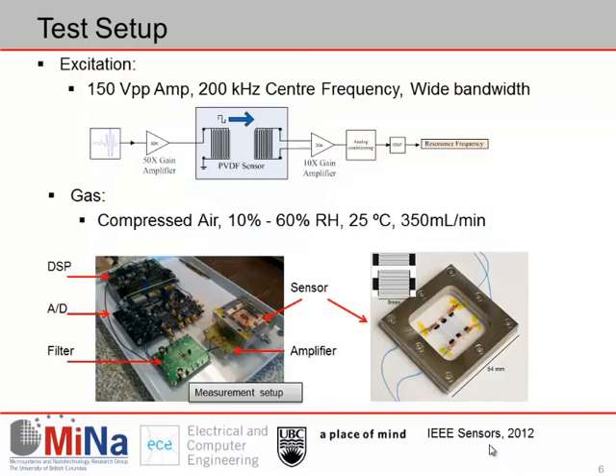Our test setup is described briefly here. We input a 150 volt peak-to-peak, 200 kilohertz center frequency signal with a wide bandwidth, and we detected a single output, the resonance frequency. As we did this, we exposed compressed air to the back, the sensing layer, with a 10% to 60% relative humidity. This is what we were investigating. And we kept the sensor at 25 degrees Celsius. So here's the picture of the sensor again.